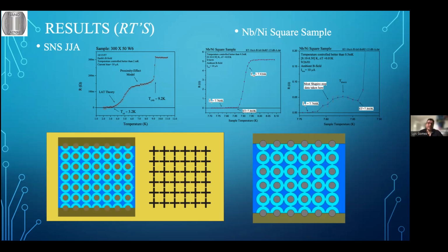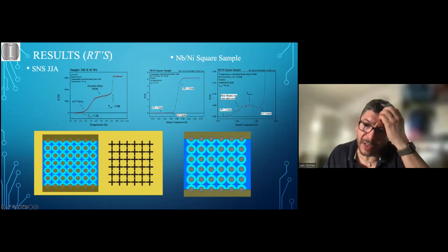Okay, so what I want to emphasize here is that in order to have one system behave electronically like the other system, the temperature of this system here with niobium and nickel has to be placed at a high location. It has to be over here. So I was very surprised to see that the resistance will go down to a minimum point, but then it will increase again. So this was really not expected.